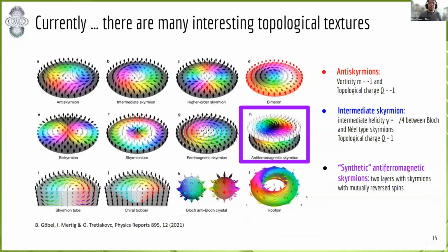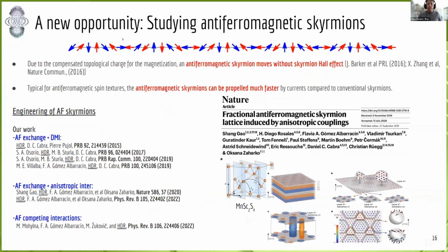This is why people are trying to use a different kind of topological texture. Here is a recent zoo of possible textures with different properties, with the idea to reduce this skyrmion Hall effect. I want to highlight only this one, the antiferromagnetic skyrmion, which is the kind of texture I work on a lot. The idea is that we can create a skyrmion lattice, a periodic arrangement of skyrmions in different sublattices, for example, of one layer. And this is a cartoon of a lateral view of one antiferromagnetic skyrmion. Blue corresponds to a skyrmion lattice, and in red is another skyrmion lattice in a different sublattice.